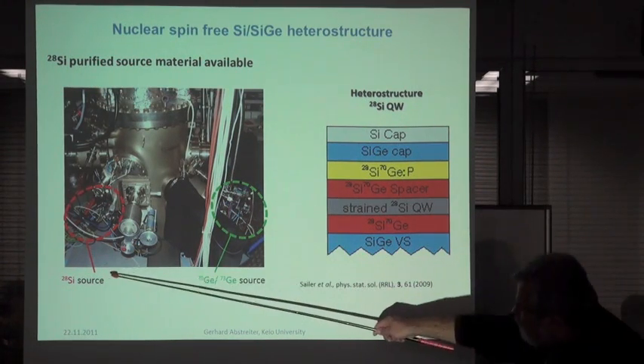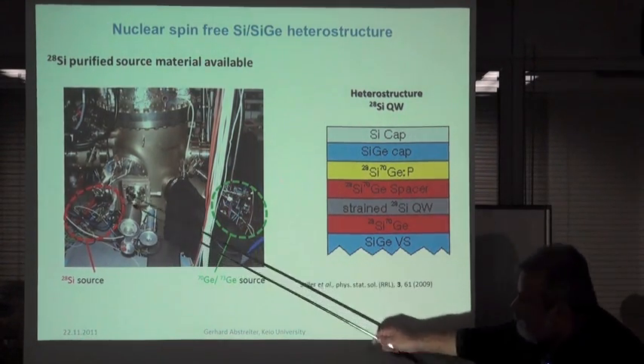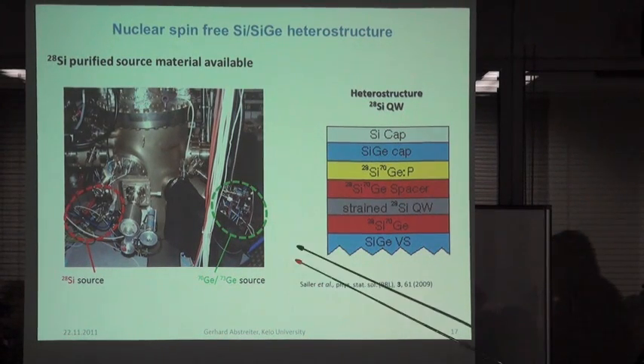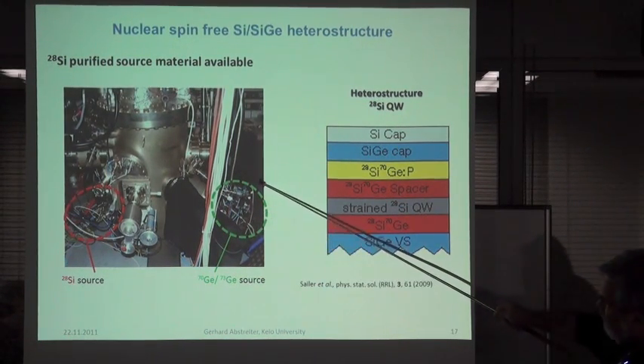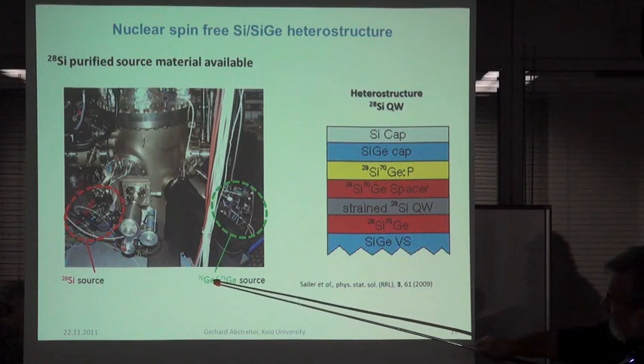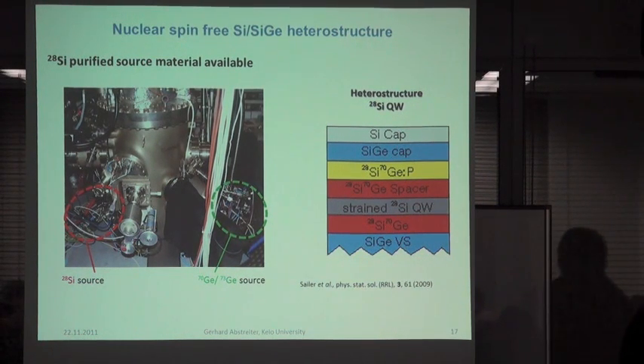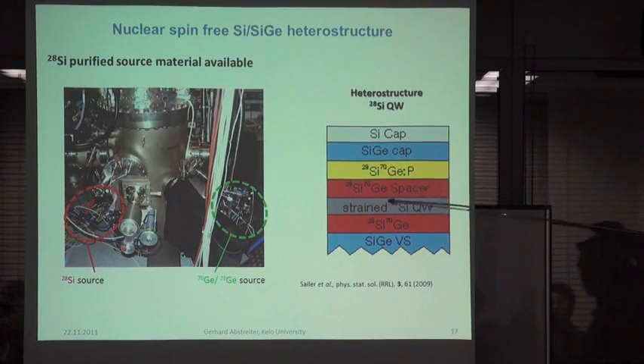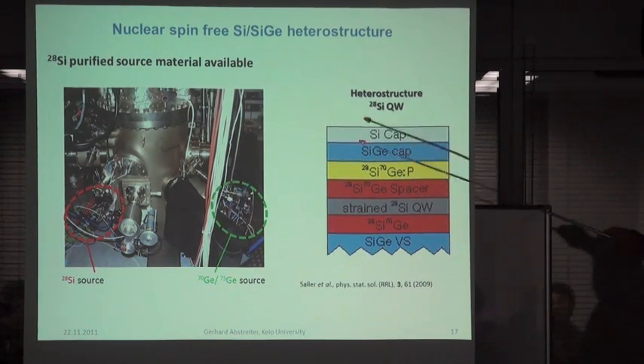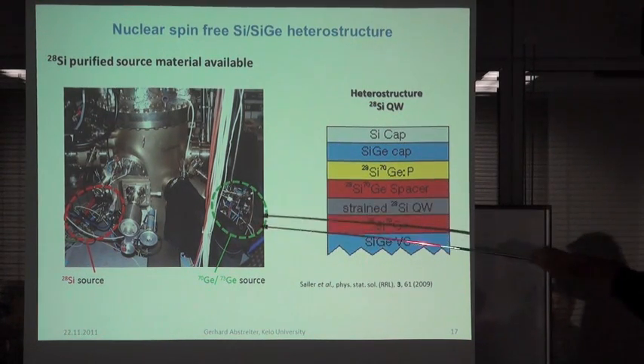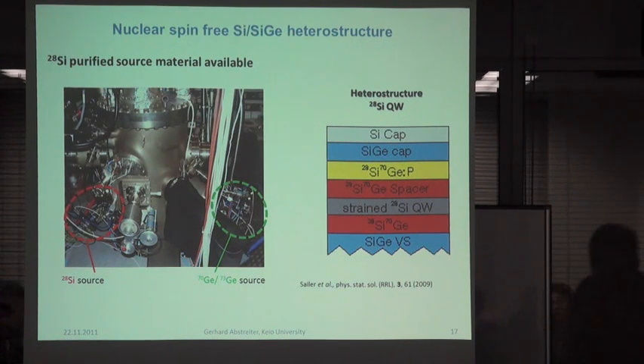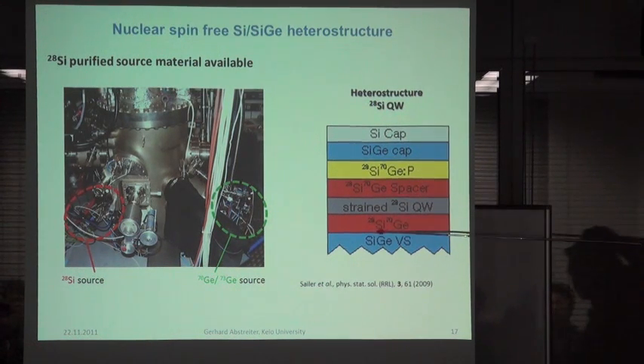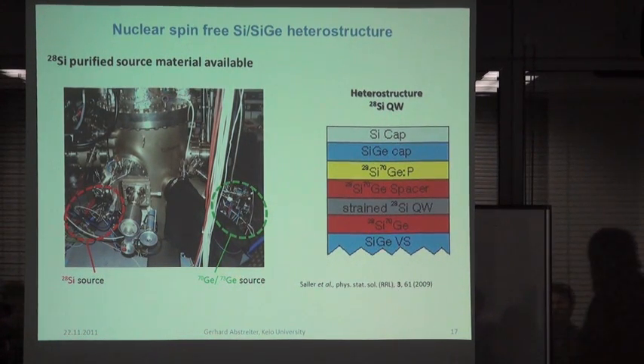This MBE machine has a silicon-28 source in here. It's a small e-beam evaporator, and has a germanium source as a Knudsen cell, germanium-70 and 73 separate here. And so what we then grow is this part isotope clean, the rest with natural silicon, so we don't use all this valuable isotope clean material where we don't have so much material. So we grow only this part isotope clean but nuclear spin free.